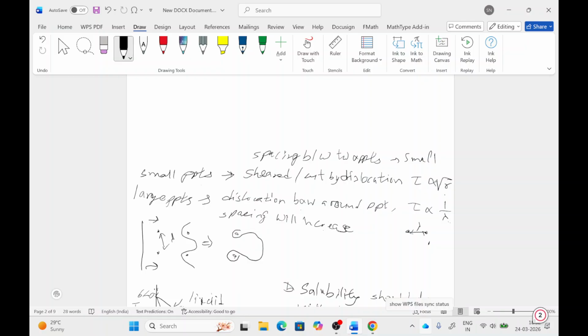Some very small dislocation loops also start forming around the precipitate with time. At some point, the dislocation line escapes from these particles, and the precipitates are surrounded by new dislocation loops. This is the dislocation line when it surpasses these precipitates. These small circles are the dislocation loops.